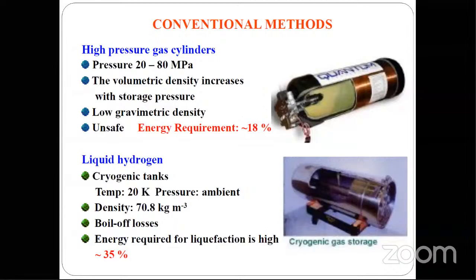But again, here also we have some drawbacks. One is the boil-off losses. Because atmospheric temperature is around 300 Kelvin, and your tank temperature inside is around 20 Kelvin, obviously you cannot arrest the heat transfer completely. Whatever insulating materials you use, some boil-off losses will be there. And also you cannot close the cylinder, because if you close it, the pressure will increase. You have to remove the vapors produced in the tank. So in this way, you lose some energy content.